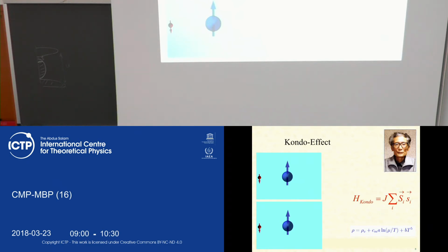Let's start with the Hamiltonian given by the first term. So there is a kinetic energy of conduction electrons. Suppose that your lattice of spins is very much diluted, and you can forget about interaction between spins and just consider independent interaction of conduction electrons with each spin impurity separately. What was discovered in certain pure metals like gold doped with magnetic ions, the prototype system for this effect, is that the resistivity goes up when you lower the temperature. It reaches some minimum, then it goes up if we deviate from this minimum and the temperature is decreased.